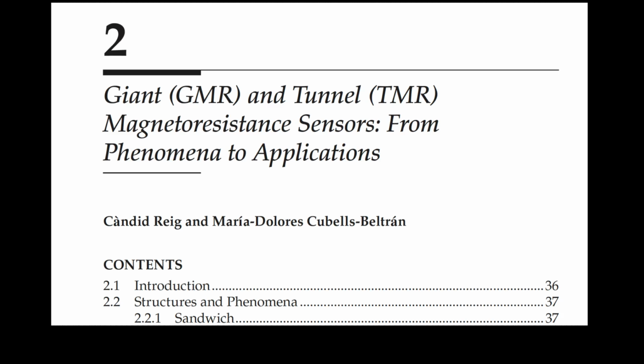Now let's talk about giant and tunnel magnetoresistance sensors, GMR and TMR. Sure, GMR sensors consist of two ferromagnetic layers separated by a conductive spacer, typically copper, with magnetoresistance ratios between 4 and 20%. TMR sensors are similar but replace the conductive spacer with a thin insulating tunnel barrier, like aluminum oxide or magnesium oxide, achieving magnetoresistance ratios up to 200%. Fabrication uses low-temperature sputtering or ion beam deposition, with magnetic fields applied during deposition to set the easy axis of magnetization. Sensor designs include spin valves, magnetic tunnel junctions, and arrays arranged in series and parallel to improve signal-to-noise ratio.